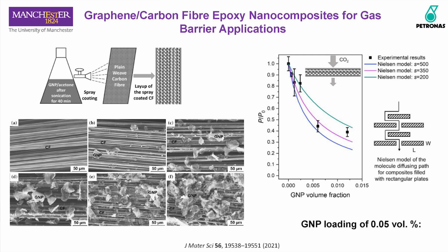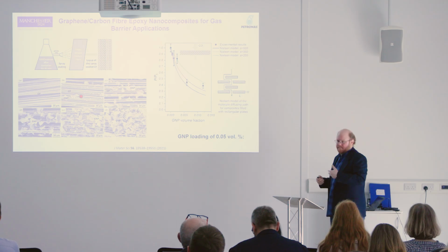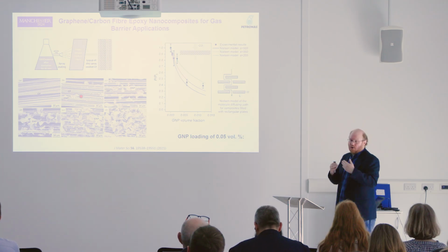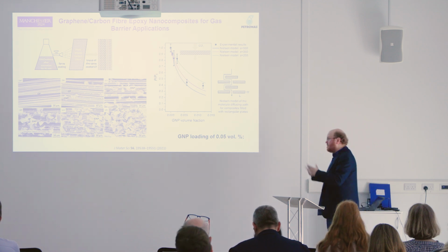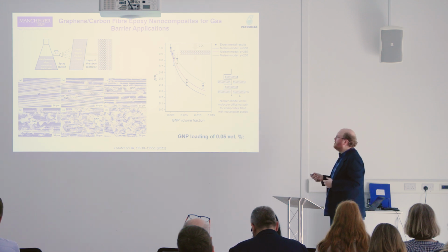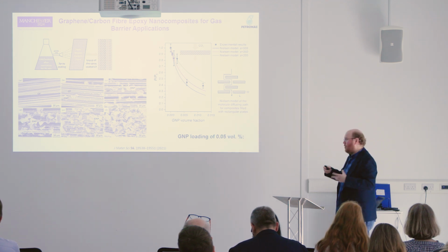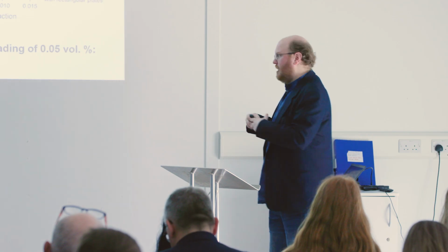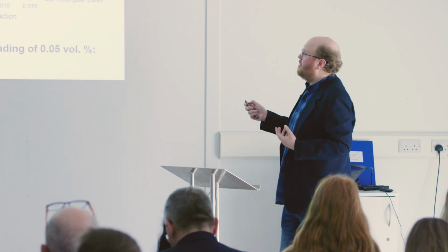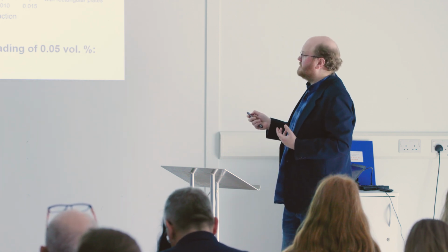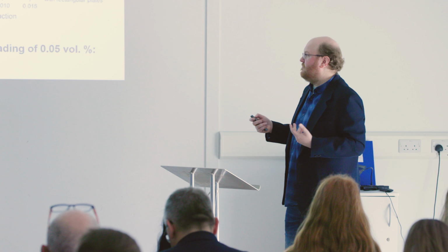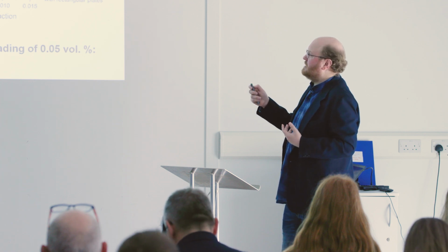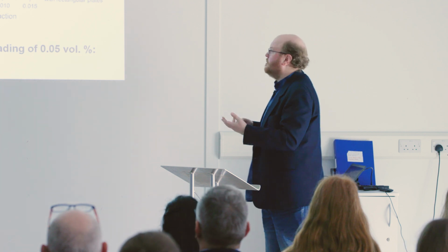We were coating carbon fiber with graphene nanoplatelets from a spray coating process, making composites out of this, and then looking at the barrier properties. So for things like pipelines or for gas storage vessels, for hydrogen storage, for example, you obviously want your composite cylinders to be able to block that gas. And we find that by having very, very small loadings of GNPs, this is 0.05 volume percent, we can actually get a significant reduction in the CO2 permeability through it.